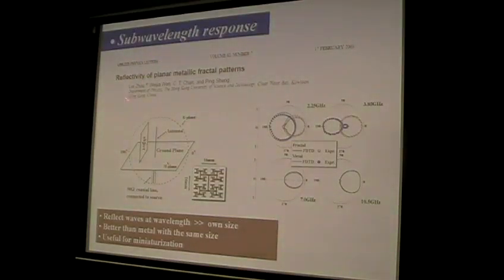Another property is that the structure can have a subwavelength response. In this 2003 APL paper, we did a simulation to demonstrate this effect. For a model antenna, which is here, we put an object here and want to block the radiation. And we measure the radiation pattern here. We found that if the object is a small metallic plate, when the half wavelength is longer than the size of this perfect metallic plate, the EM wave cannot be blocked.